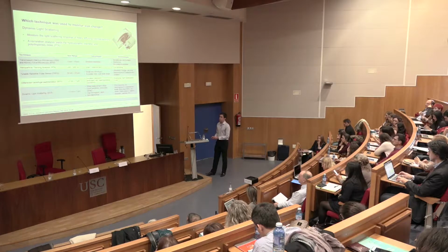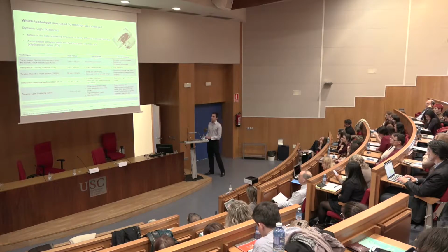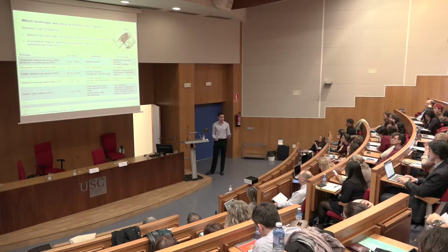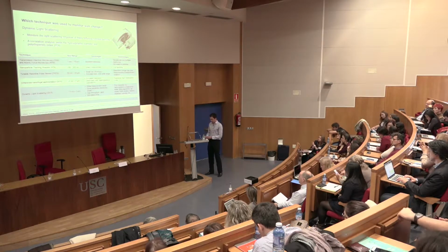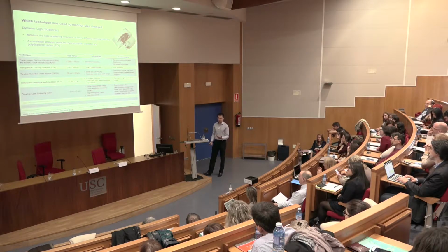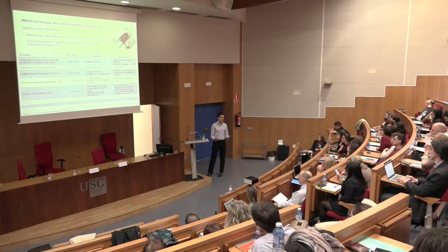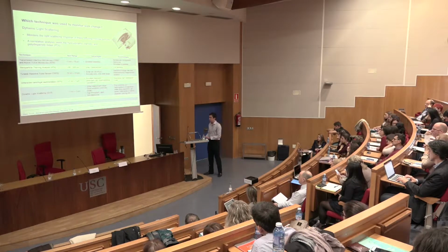This leaves us with a couple of techniques: DCS, which is a very good technique, but is expensive and high maintenance, or DLS. We chose DLS because of the wide measurement range of the instrument, the good sensitivity, so it can see monomers and dimers, and also it's high throughput, it's rapid, and it gives us a non-destructive measurement. So we can measure these particles and then directly put them into another assay or into the animals.